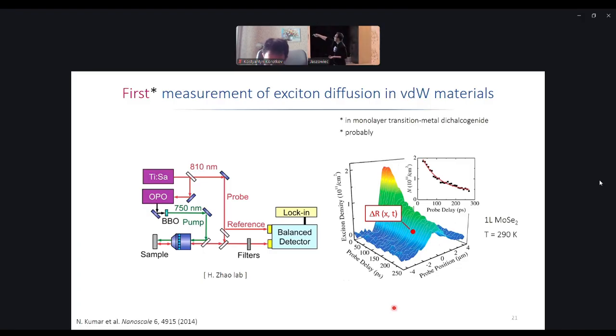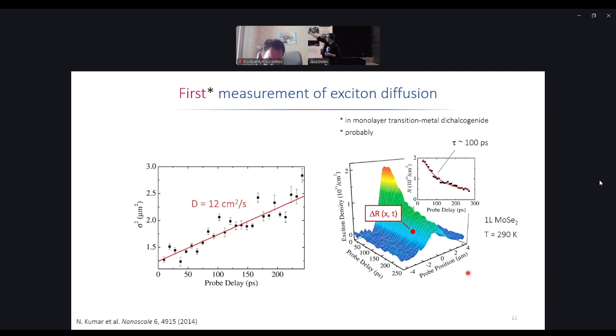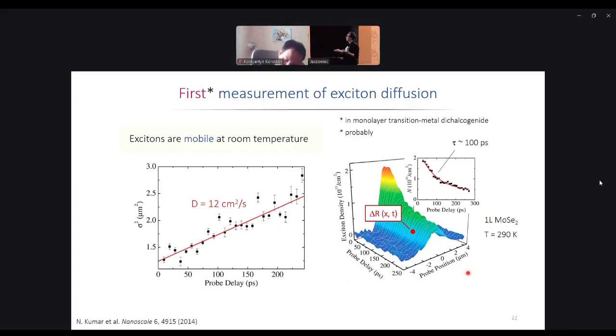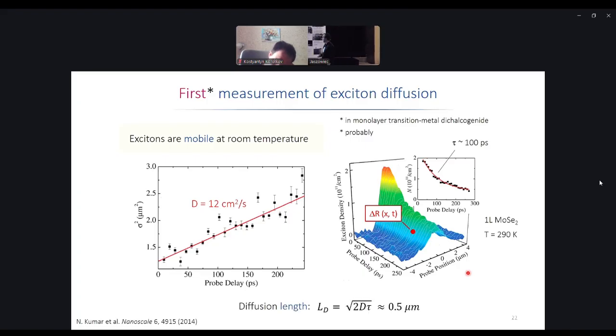You see a decay of this curve over time, and now one can evaluate the broadening. And if the broadening is evaluated, in this particular case, you get a diffusivity coefficient of 12. We'll talk a bit later about what this number means, but it seems that there is a linear diffusion at room temperature for this monolayer material. So the observation here is that excitons in this particular case are mobile at room temperature. Yeah? That's what it is, and then one can think about what the diffusivity actually implies.